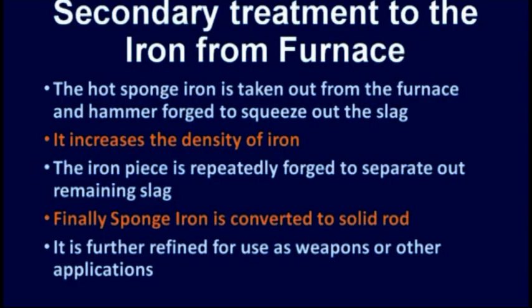The hot sponge iron is taken out from the furnace and sent for secondary treatment. Secondary treatment is important because this sponge iron contains a lot of slag particles. By hammer forging, these slag particles squeeze out and the sponge iron becomes free from slag and forms a solid iron rod.